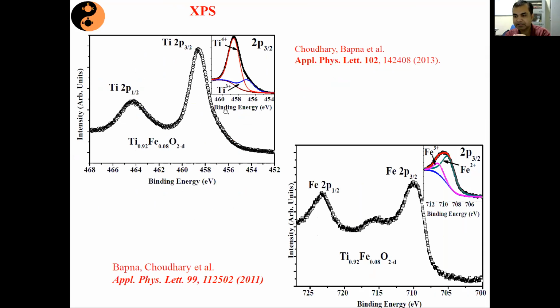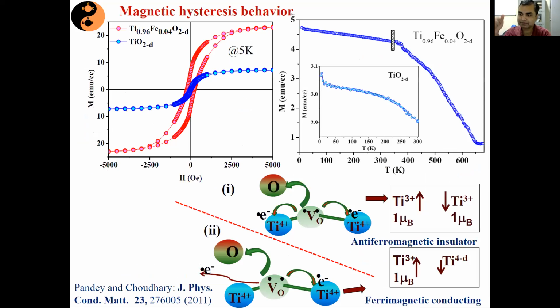Then how do I confirm that iron is substituted and is not forming a cluster of its own? Remember, if iron was in cluster phase, then the kind of bonding between iron and iron would have been metallic bonding. But if you probe its ionic state by photoelectron spectroscopy, what it tells you is that iron is not present in the metallic state, rather it is in ionic state. Okay, so that means iron is not forming a cluster of its own. So that is one thing which is very important to probe. Now I confirmed that with iron doping, iron was not forming clusters.